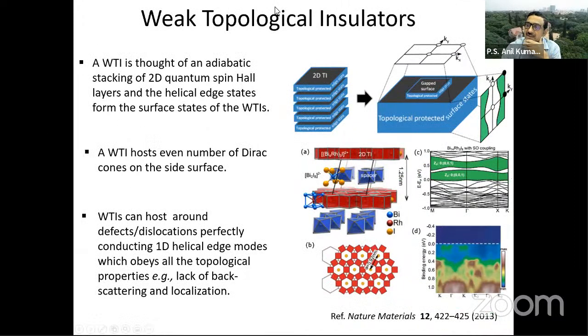So this is about a weak topological insulator. The weak topological insulator can be thought of as two-dimensional quantum spin Hall layers stacked together. If you take this stacking, you will have topologically protected surface states only at the side surfaces, whereas the top surface is a dark state. That means there's no metallic surface state at the top and bottom surfaces. But on the side surfaces, you have this topologically protected state, and it has been shown that you have an even number of Dirac cones on the side surface.